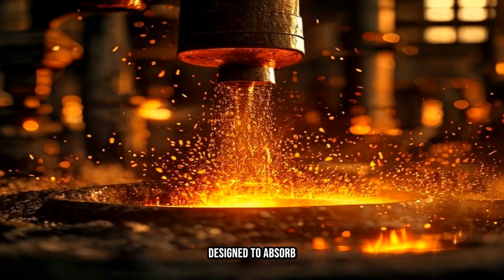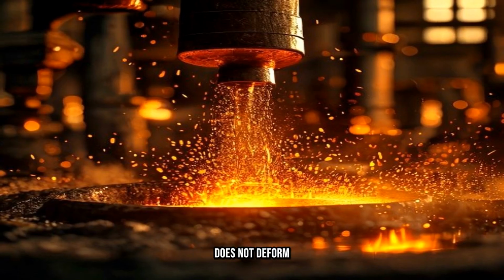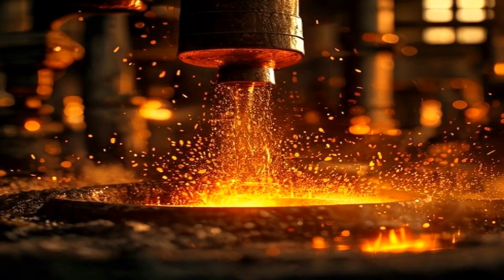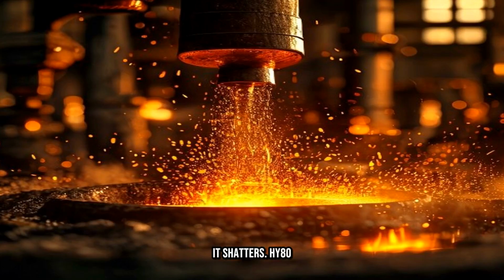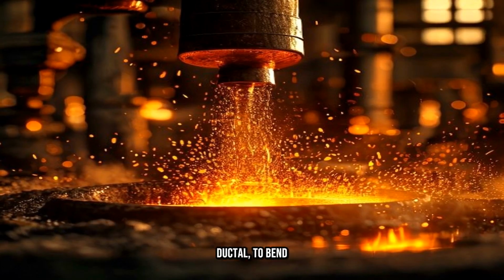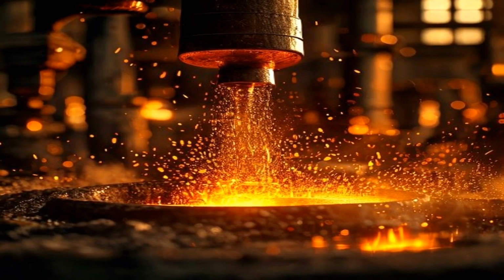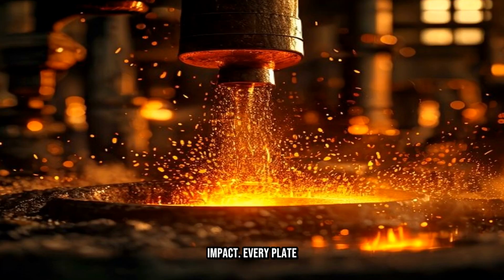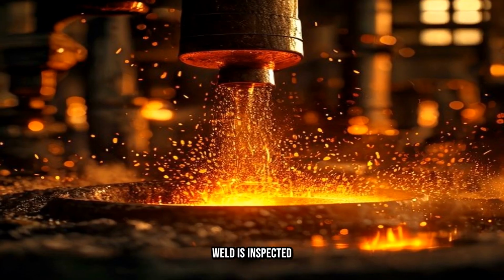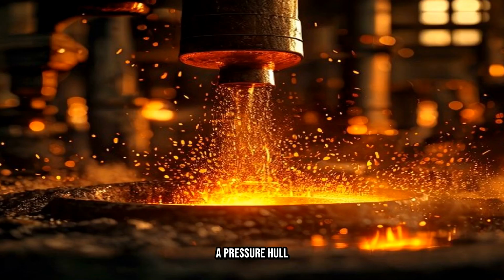They are alloys designed to absorb energy without becoming brittle, which matters because brittle steel does not deform before it fails. It shatters. HY-80 and HY-100 were engineered to remain ductile, to bend rather than snap, even at low temperatures and under impact. Every plate is tested. Every weld is inspected by ultrasound and X-ray.